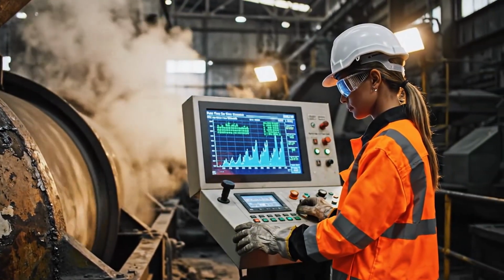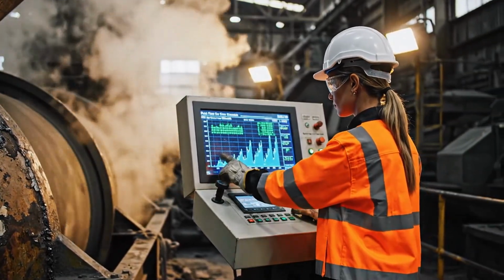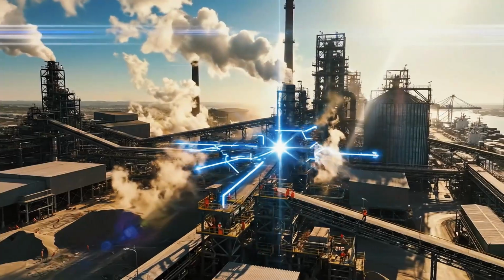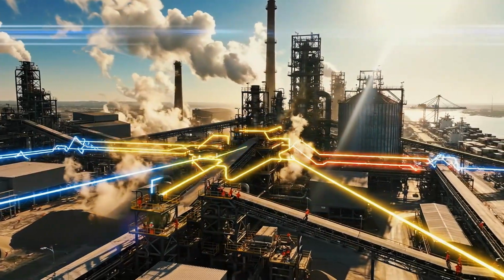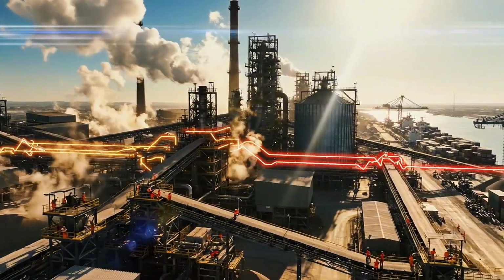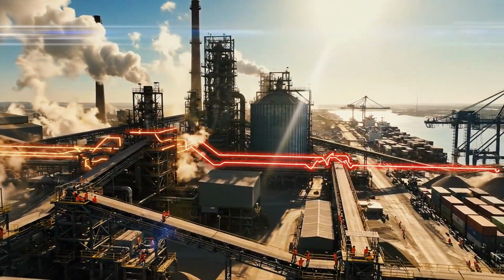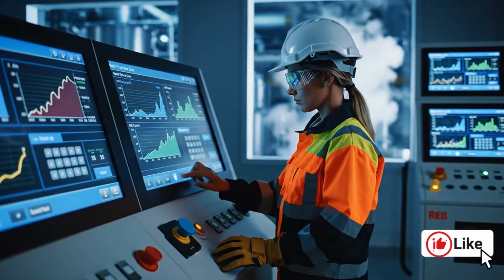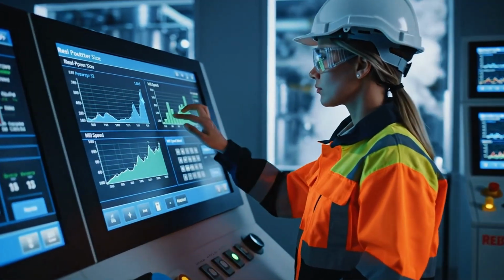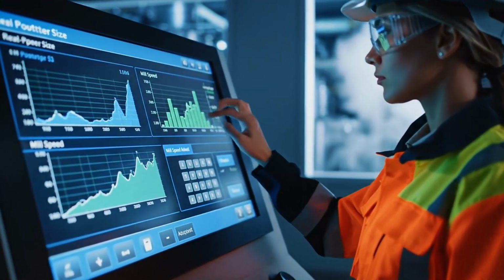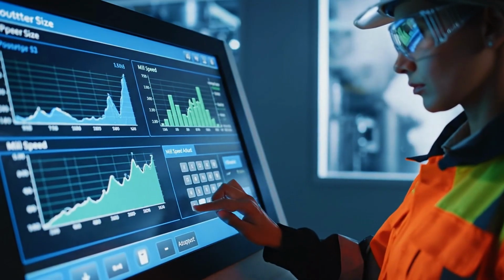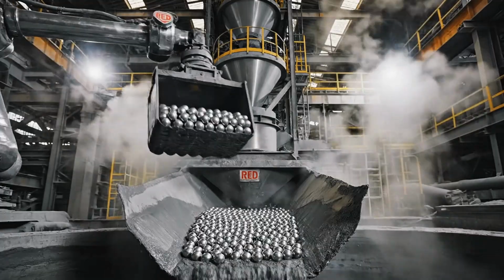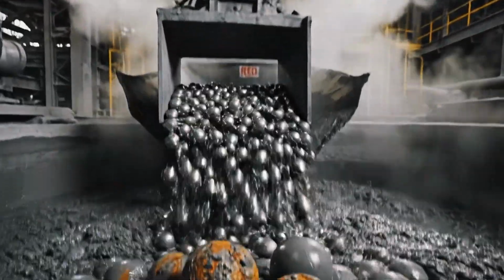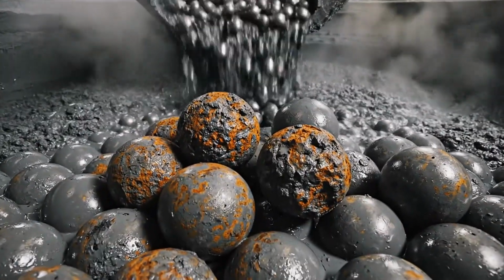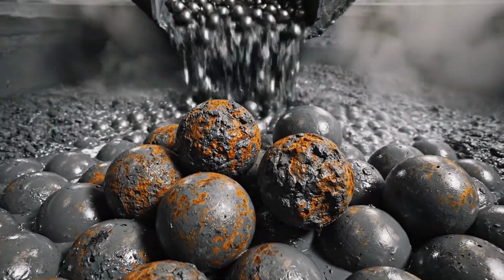This grinding stage is where the real precision begins. The particle size must be exactly right. Too large, and the gold remains locked inside rock crystals. Too small, and the subsequent chemical processes become inefficient. Advanced sensors monitor particle size in real time, adjusting mill speed and adding fresh grinding media as the steel balls themselves wear down and become part of the ore slurry.